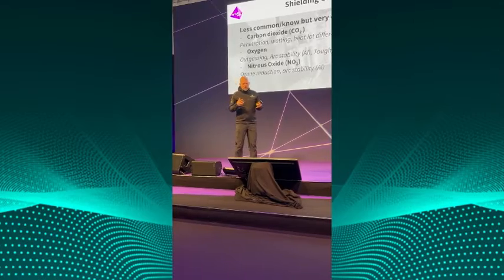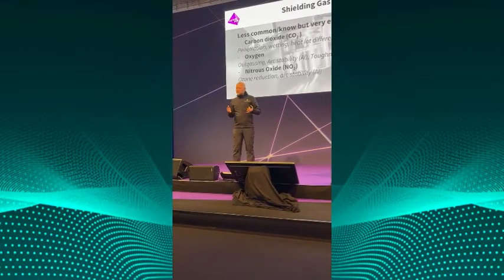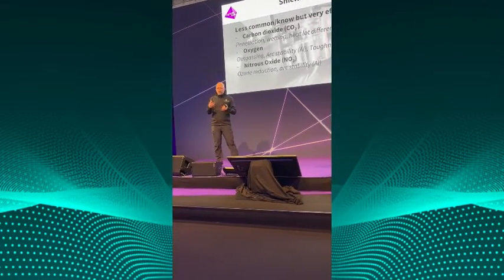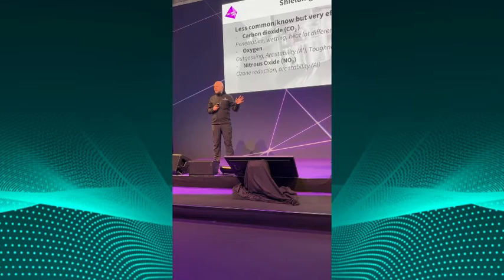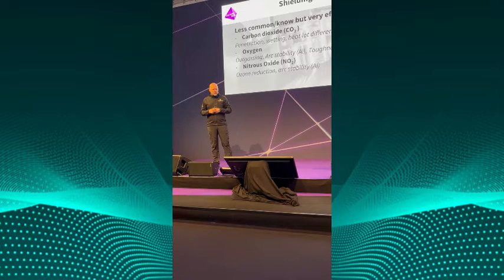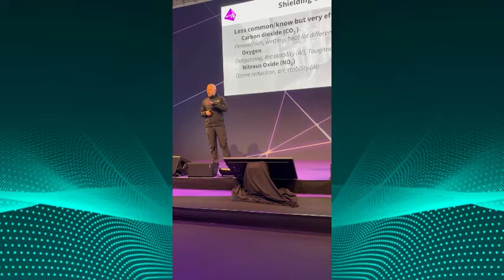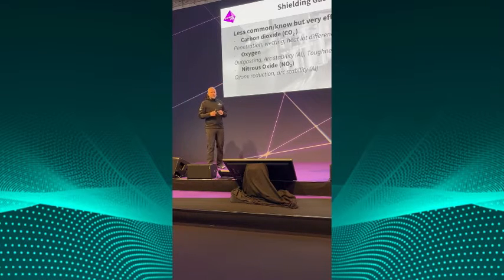There's also the possibility to add oxygen. It improves outgassing and arc stability in aluminum welding, and increases toughness in carbon steel. So it helps with forming acicular ferrite, a special composition, where you have an increased toughness without embrittlement by adding oxygen in a carbon steel weld. So people might think, well, adding oxygen will cause porosity. That's plainly wrong. Oxygen almost always doesn't cause porosity. It's hydrogen or nitrogen which causes porosity. So somewhere in the translation of air and oxygen, someone mixed something up.